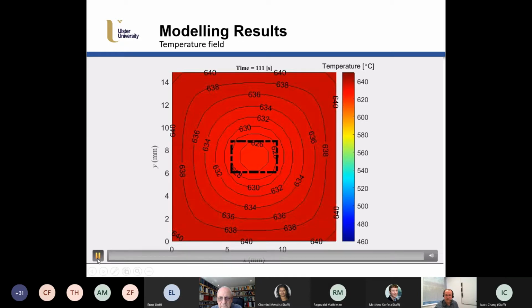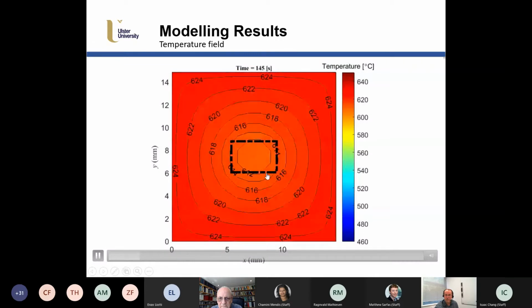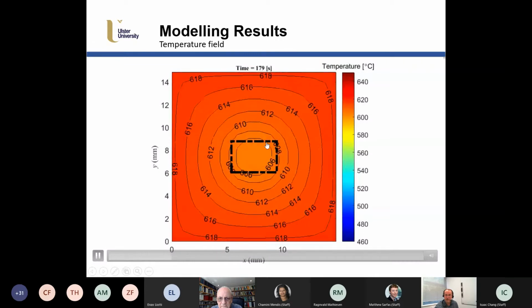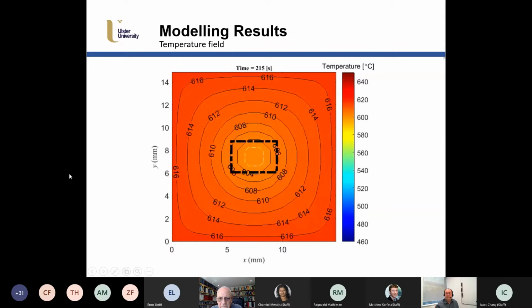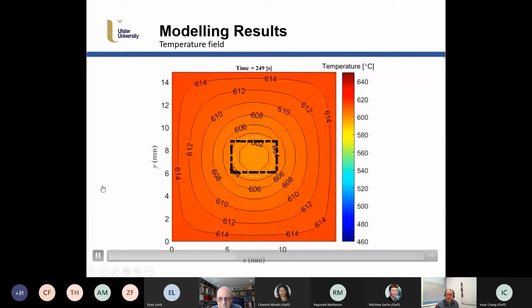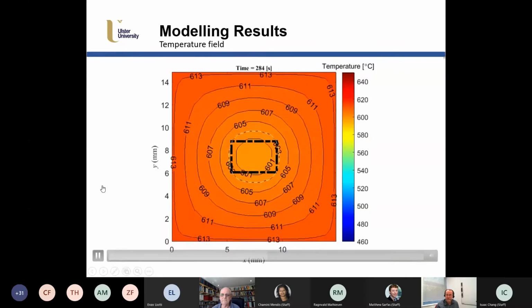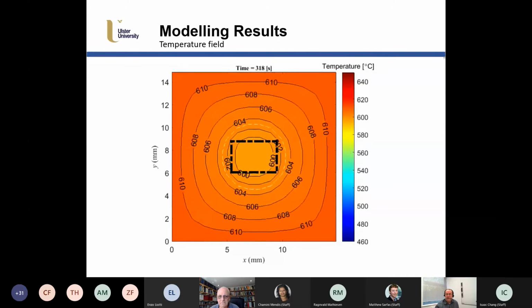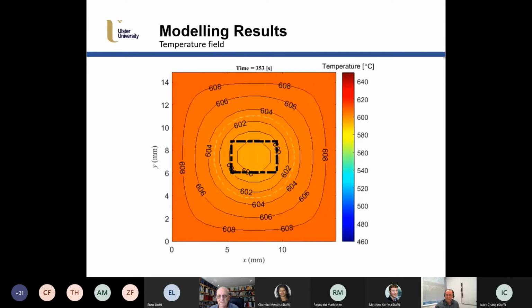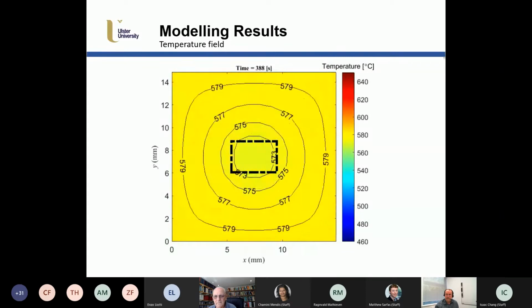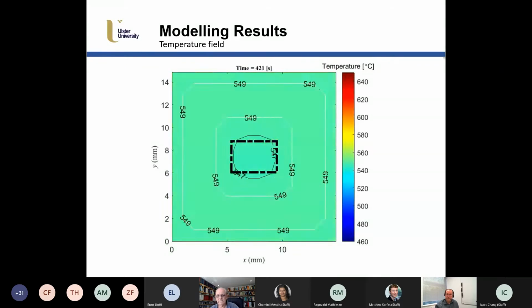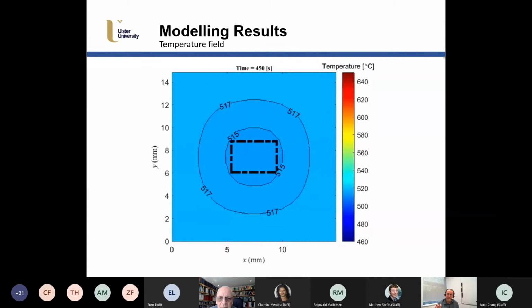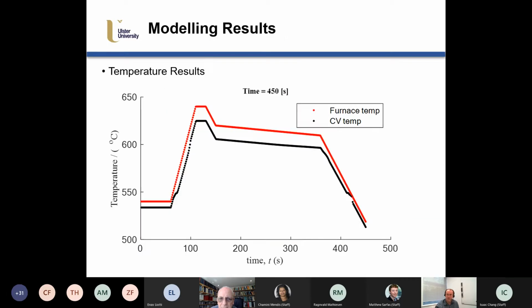So to show you the field of view, the X-ray only looks, anything you see here is in this square box. So we had to model the entire domain. The white broken line that you see there is the liquidus isotherm. And so somewhat similar to the botanist that goes out to the field and throws a wooden frame and then counts the fauna within the wooden frame, we're looking at this box in the middle, and we're trying to get statistics in this box for the nucleation. And so that's what we're trying to do here.